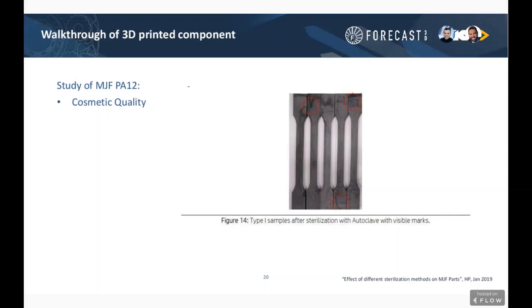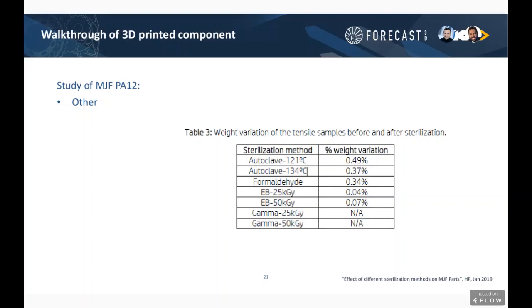The last thing that we consider here is the actual potential for the part to absorb any materials. And this is just a sample of what those results could look like. So in an autoclave, when it's steam and heat oriented, you're going to see a little bit more potential for gaining material or absorbing some water. The formaldehyde is in a similar situation where it's a chemistry that potentially can be added, and you have to assess the risk of these percentages for your application to see if it matters. The other ones you don't see as much of an increase purely because you're generally just applying energy.